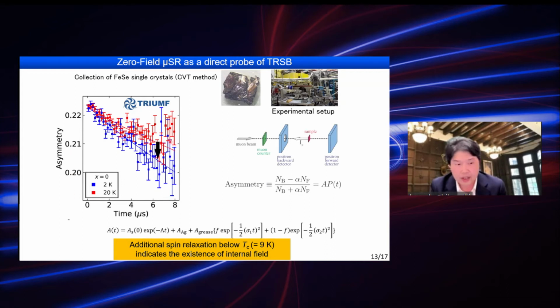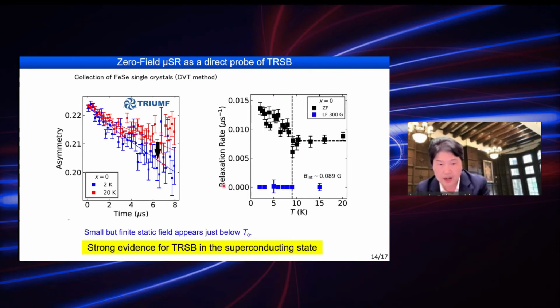The red is at 20 Kelvin, above the superconducting transition temperature, and the blue is at 2 Kelvin, inside the superconducting state. As you can see, we have faster relaxation at low temperature in the superconducting state. From these data, we can extract the relaxation rate as a function of temperature, and we find that the relaxation rate increases below Tc, which is about 9 Kelvin in this case.